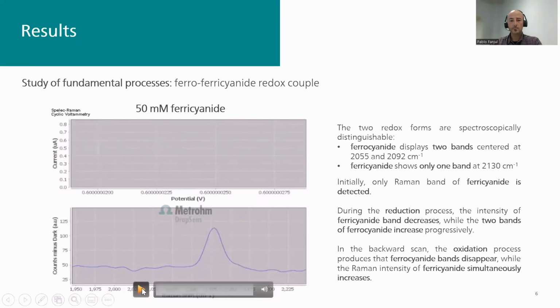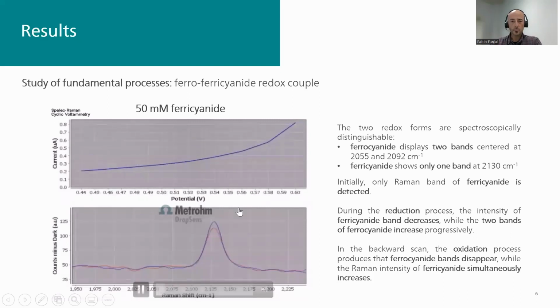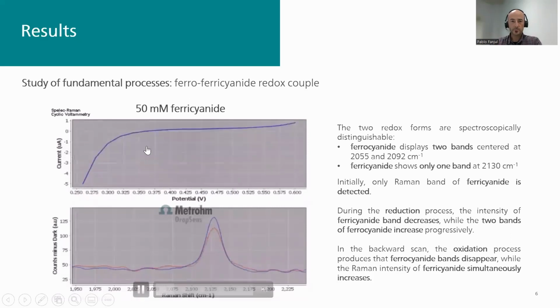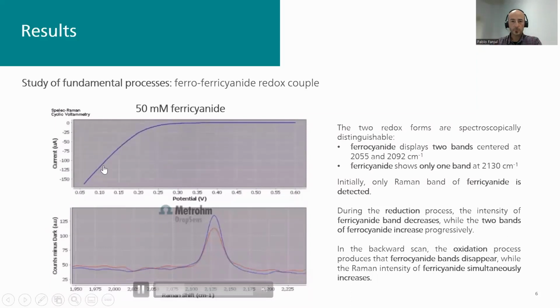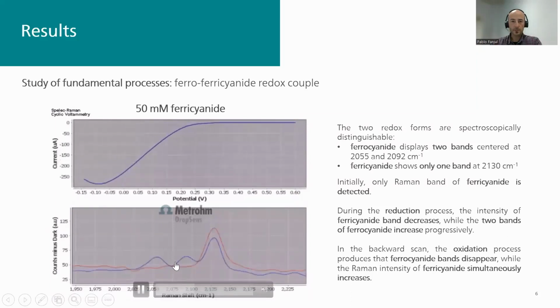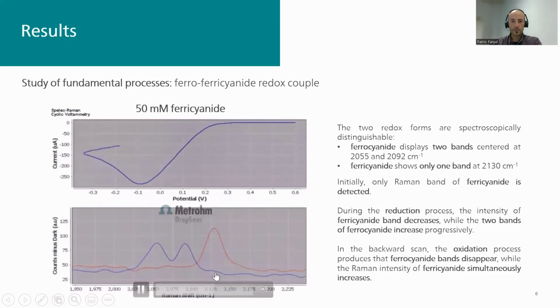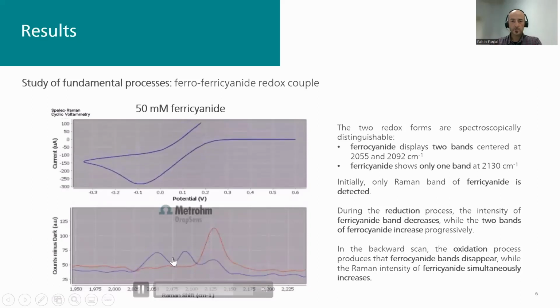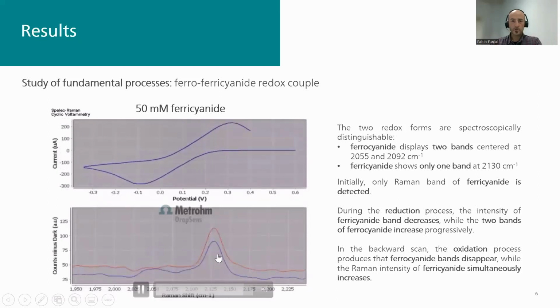So we can see it with the video. Here we have the starting Raman spectra. We reduce iron 3 to iron 2, and then two Raman bands start to arise. The other one is completely deleted. And then in the oxidation process, we can see that these two bands are going down, and the first initial one is going up. Okay, so it's an easy example of how to use the Raman signal to follow an electrochemical reaction.